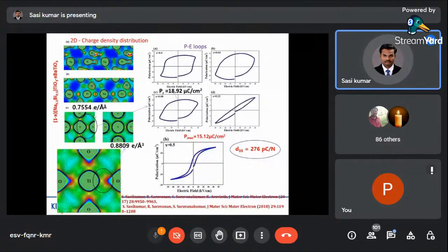So here the bonding between the titanium and the oxygen atom possesses higher mid-bond electron density, 0.75. This is considered as a covalent bonding between the Ti and O atoms, which also gives higher remnant polarization value compared to other samples.